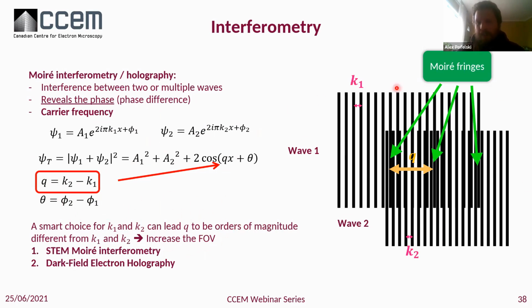On the right, you have this schematic. You have the overlap of two periodic elements with slightly different wave vectors or periodicities. So this will be the inverse regarding the wave vector. If you overlap them, you're going to generate some Moire fringes, just by considering the overlap, that have a different periodicity related to this. As you can see here, the periodicity of both is small and the periodicity of Q is large. That's exactly what we're going to be trying to use to expand the field of view, by using these Moire fringes instead of directly using the fringes from wave 1 and wave 2. So I'm going to present two methods.